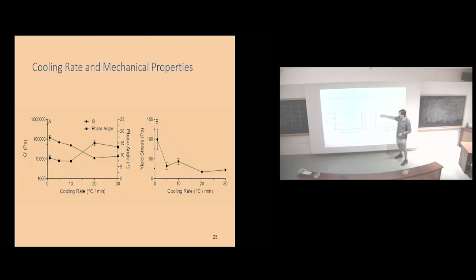For example, we measured the yield stress of the oleogel. And I have a lot more data, but I decided not to show you. Anything you do to it, like shearing in order to fix it and to help it, decreases the yield stress. So you go from that brittle material to something that is a lot weaker. Look at that as a function of cooling rate. And also the G prime of these things can be relatively high for such low concentrations. Forget the fact that we have phase angle here, but look at the G prime. And if you increase the cooling rate, even though you make those big structures, you actually decrease the G prime by one logarithmic unit there.